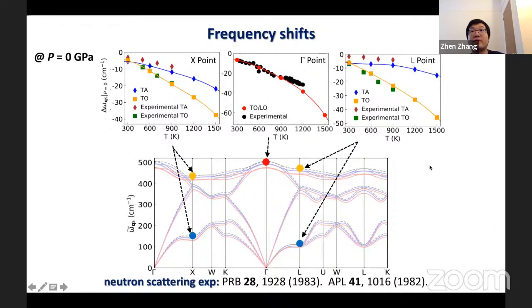As you can see, the temperature-dependent phonon frequencies obtained from phonon quasi-particles agree well with neutron scattering experiments for different Q points in the Brillouin zone. This validates the present phonon quasi-particle approach.